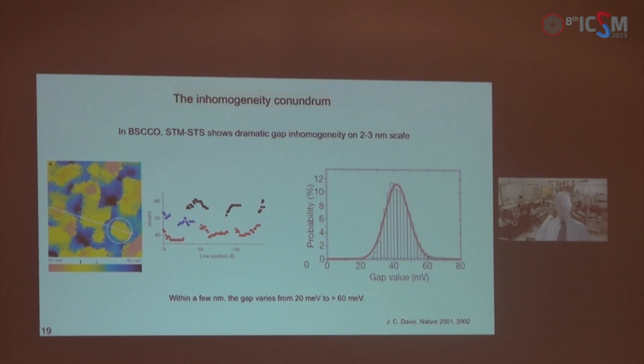At this point, I would like to mention that after our 2016 paper that showed the demise of superfluid density with overdoping, many explanations were proposed. The majority of these actually speculated that this is somehow due to disorder, one way or another. And indeed, the thought did occur to me early on, but did not seem very likely, simply because the coherence length in cuprates is so short that most of the cuprate samples are in the clean limit. You would need disorder that is significant on the scale of 1 nanometer and then goes to much denser than that.